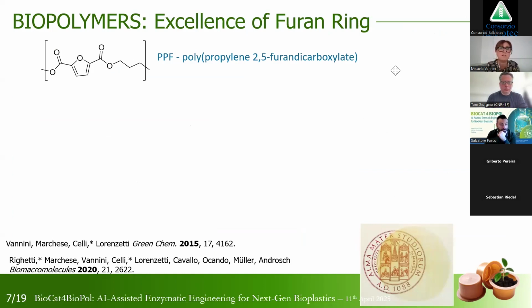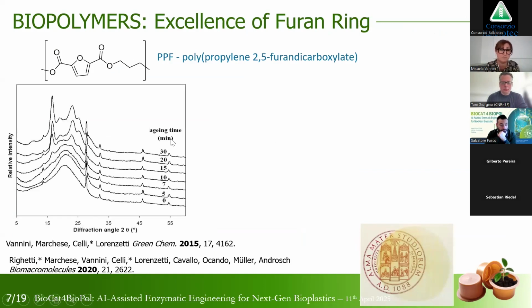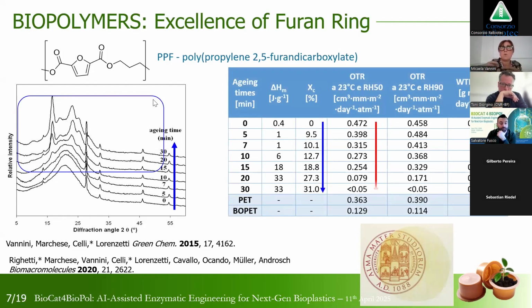For example, we studied polypropylene furan dicarboxylate, and when PPF is treated at 135 degrees, we observed that it develops a crystalline phase, in particular after 30 minutes, visible here with X-ray diffraction. When the crystallinity increases, we observed that the barrier also increases.